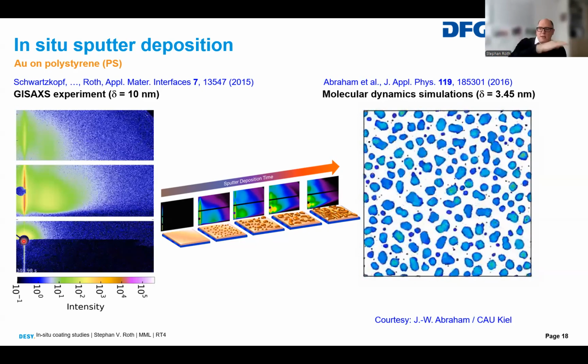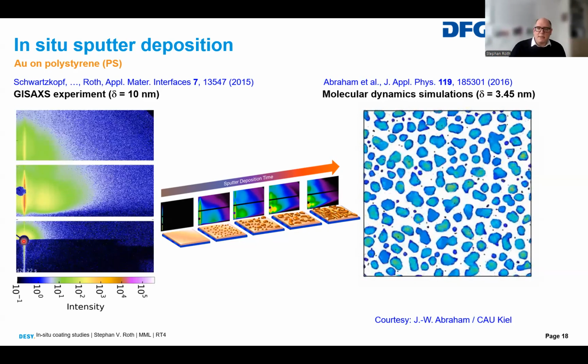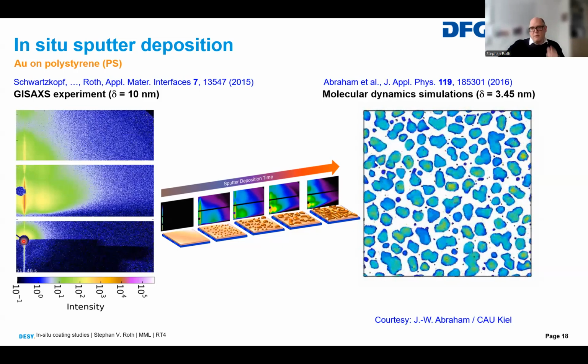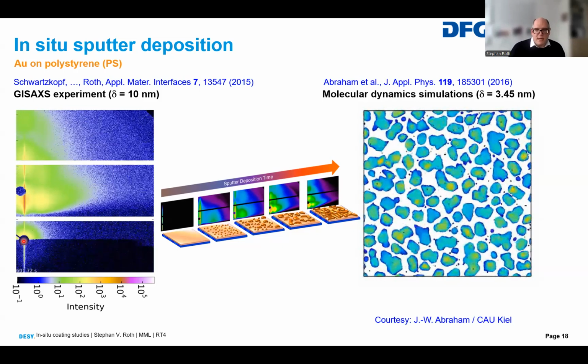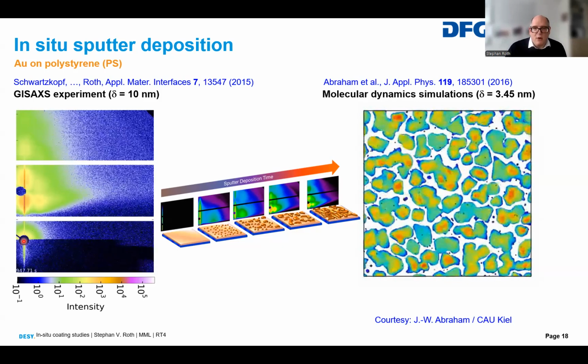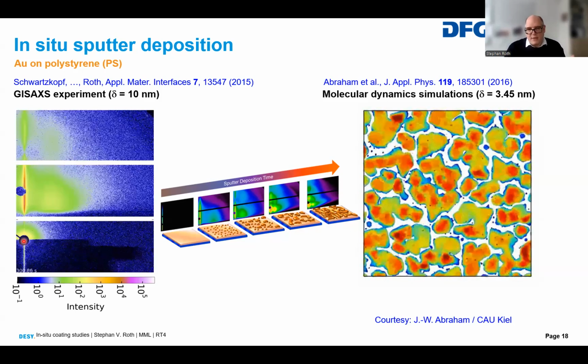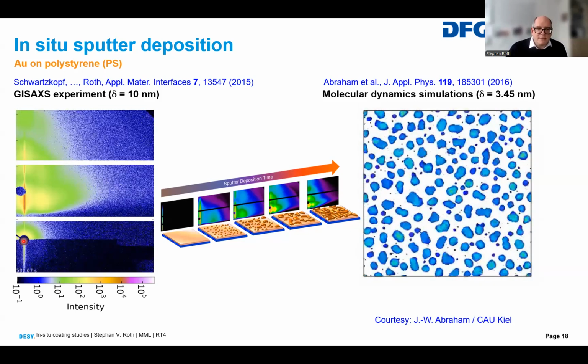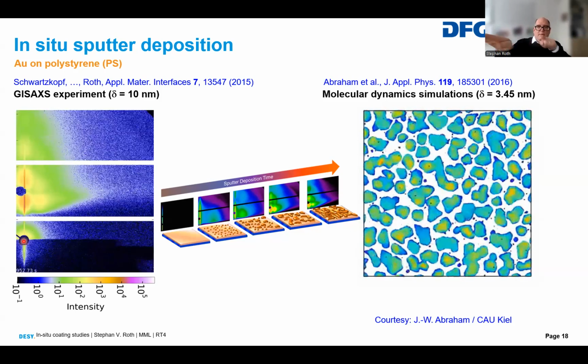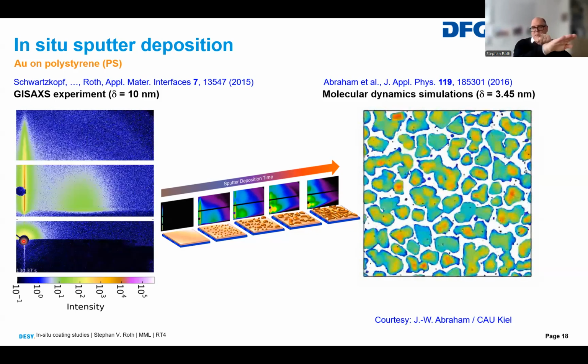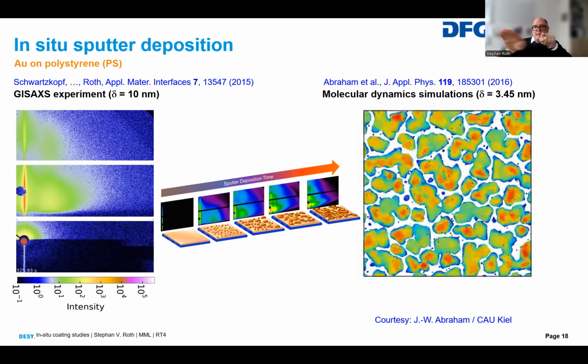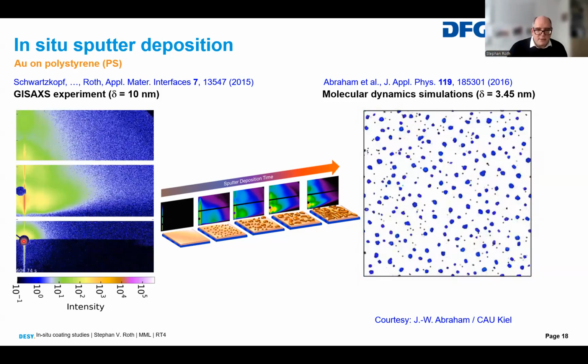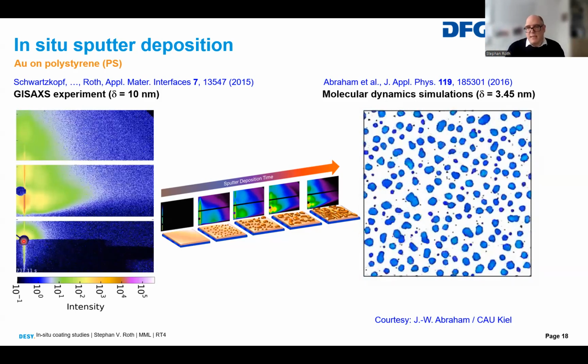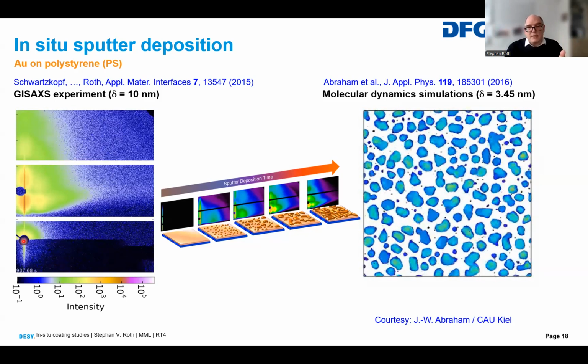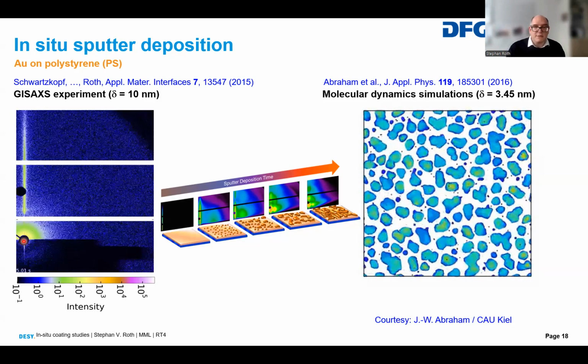When we go to third generation sources, the intensity is so high that if we would stay on one position, we would burn the sample and effectively alter, via radical formation, the growth of the clusters. This is why we move the sample through the beam, which stays constant, since you cannot move the synchrotron. By this we are able to distribute the dose on the sample surface and really tell you that this is the real cluster growth, unaffected by the X-rays.